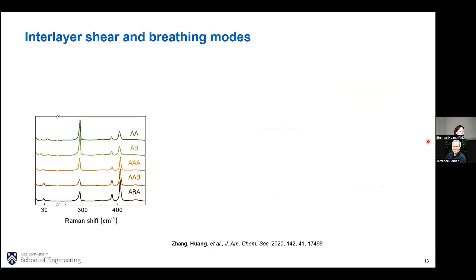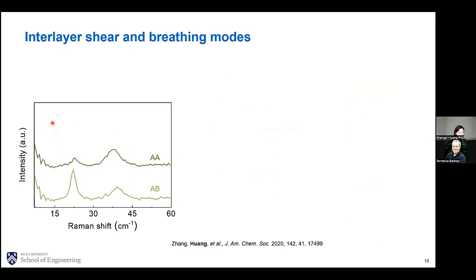So now if we look at these Raman spectra again, you can see in addition to these high frequency Raman modes, there are actually some very small modes over here in a very low frequency range. If we zoom in for the bilayers, we can see there are 2 modes, one at around 22 inverse centimeter and the other one at around 38 inverse centimeter. These modes actually correspond to the interlayer Raman modes.